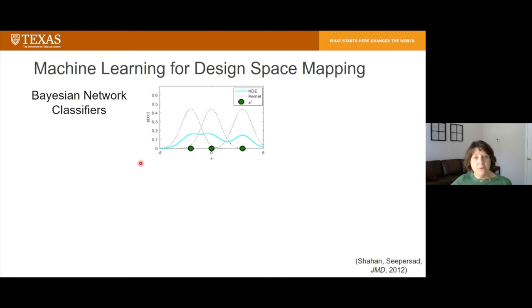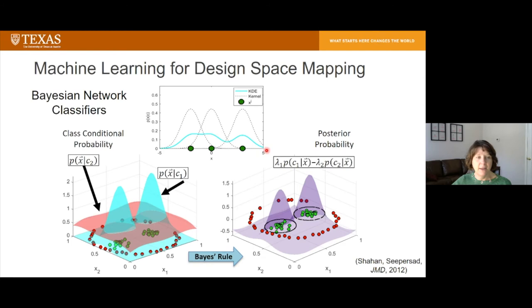So these classifiers are borrowed from machine learning. Basically, if you have a set of, let's say, high performance designs, then you can center Gaussian kernels on each of those points and then aggregate them into a kernel density estimate. And so you can see here a kernel density estimate for the high performing class in green or blue, and then in red, you can see the low performing class. We apply Bayes' rule to that to establish a posterior probability that tells us, for any point in space, the probability that it's a high performance point versus a low performance point. And then we can use that to distinguish between different regions of the design space to identify good regions.